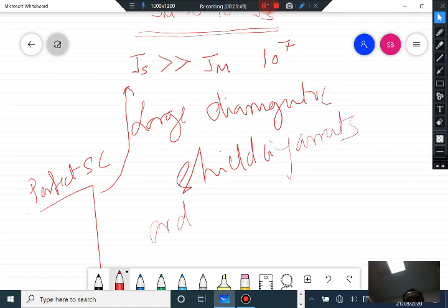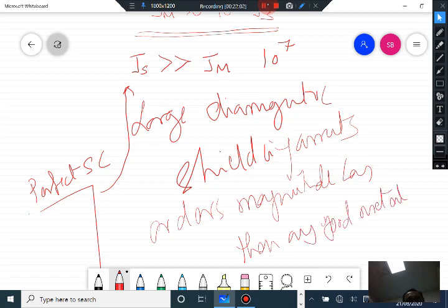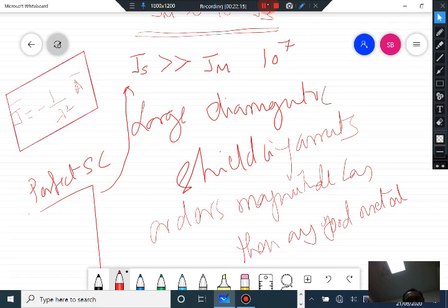The diamagnetic shielding currents in a superconductor are orders of magnitude larger than in any good metal — metals cannot show such large shielding currents. With these very large shielding currents, you get perfect diamagnetism, expressed by J = -(1/λ²) A, London's equation, which gives rise to perfect shielding in a superconductor. The negative sign shows that these are screening currents, so the external field is shielded out from the interior of the system.